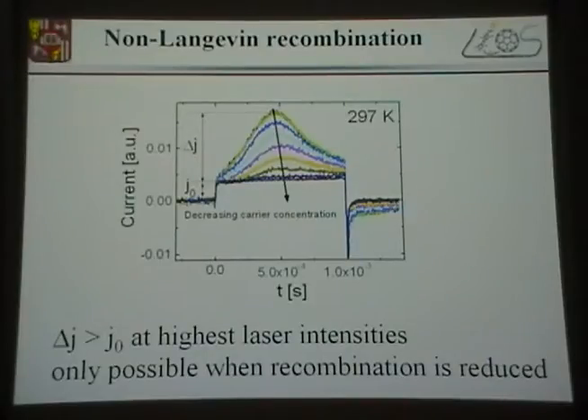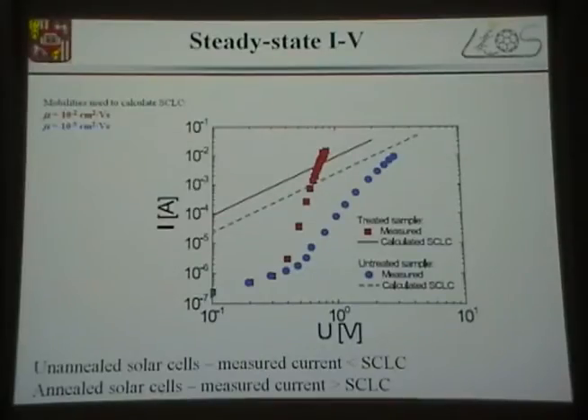You for sure know that the recombination is non-Langevin. And this non-Langevin recombination is nothing new, nothing special. It's been studied in the 60s by Mott, by Mark and Lambert, by Rose, by many, many famous physicists. The nice, interesting thing is that if you measure the photocurrent in forward, the dark injection current in forward bias, you see that the current levels are extremely high.